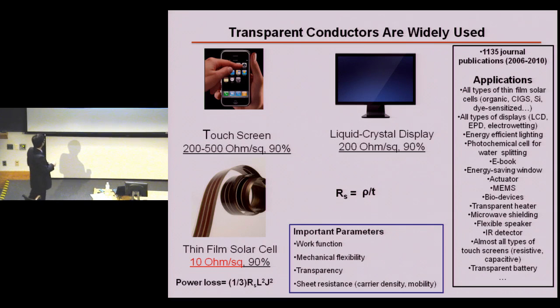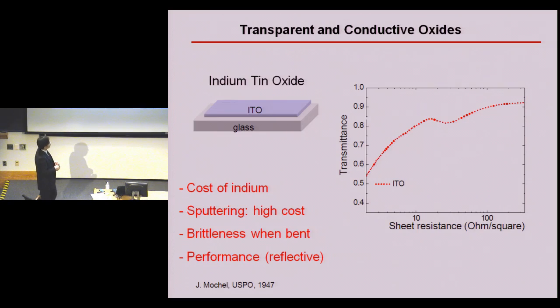But on the other side, for thin film solar cells, you would like to have a smaller sheet resistance. Otherwise, you are going to have a power loss, which is associated with the sheet resistance as well as the current density. So among many other parameters, the two most important parameters are one, the transparency, and the other, the sheet resistance. So current technology is based on tin-doped indium oxide.